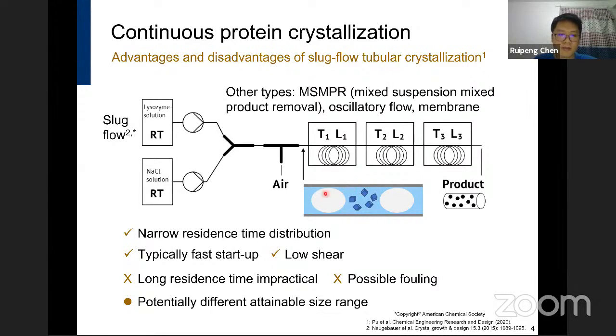Apart from that, it also typically has fast startup and low shear. This is important for protein crystallization because proteins are considered fragile under shear. But the shortcomings are that long residence times are typically impractical due to the limited tubing length, and fouling is also possible. It has also been reported that a different attainable size range can be achieved for a continuous process compared to a batch one.